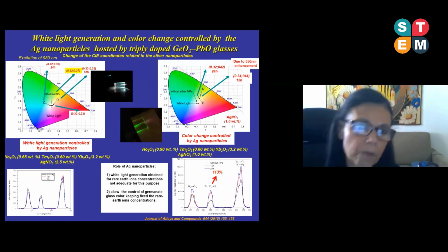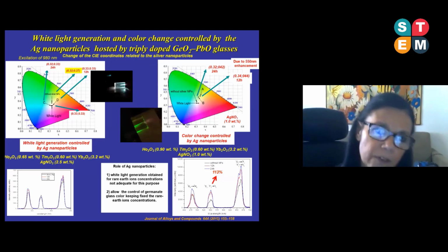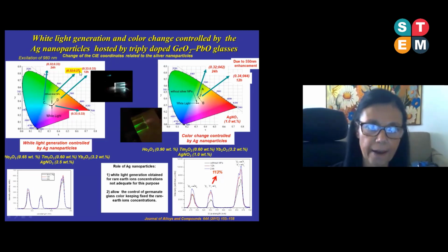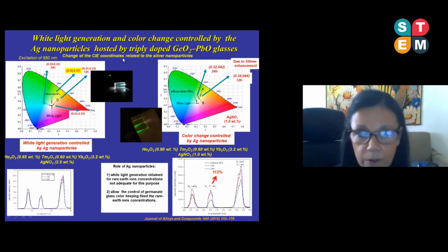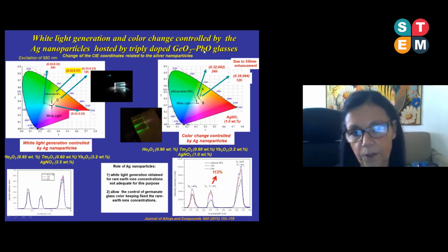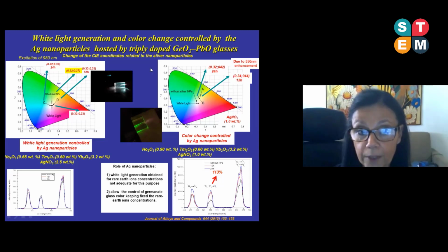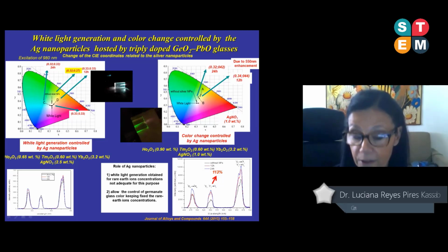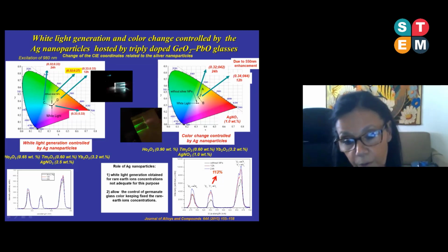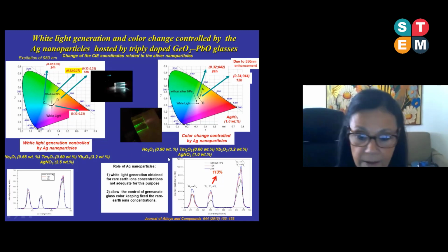It was possible with this material to demonstrate white light generation and color change controlled by silver nanoparticles using this material and three different rare earth ions that are shown here: ytterbium, thulium, and holmium. It was possible to obtain a strong white light, strong green light by specific combination of these three rare earth ions and the silver nanoparticles.